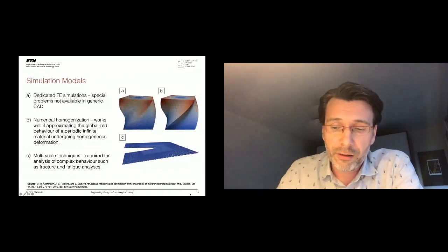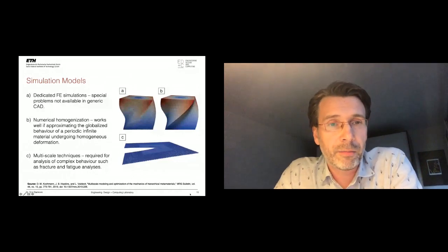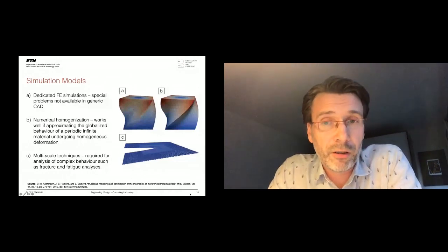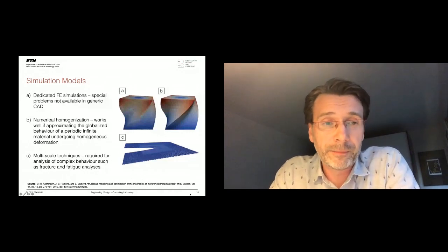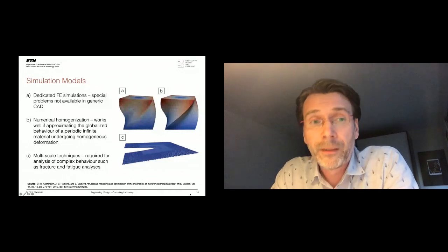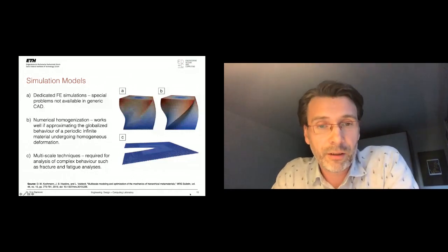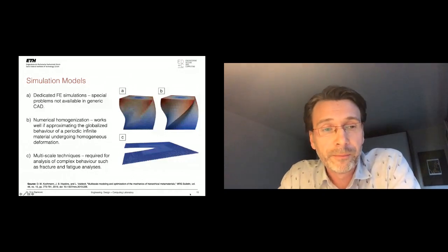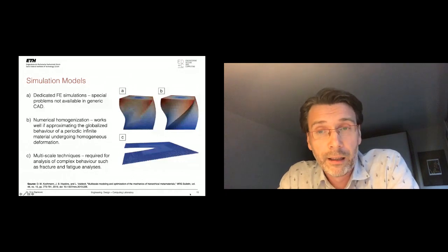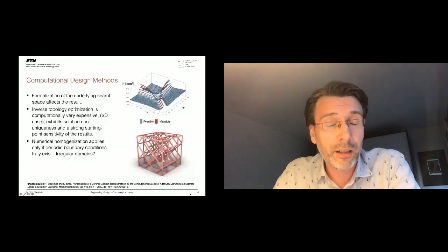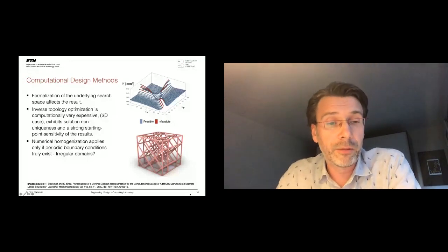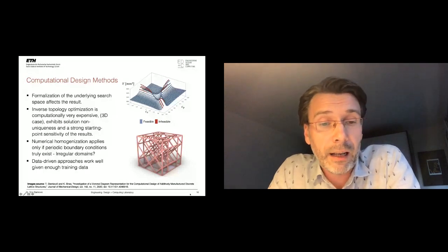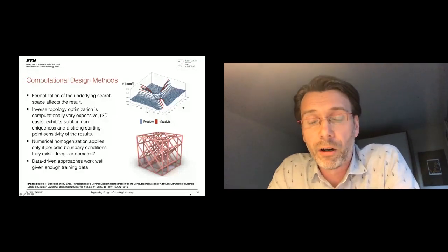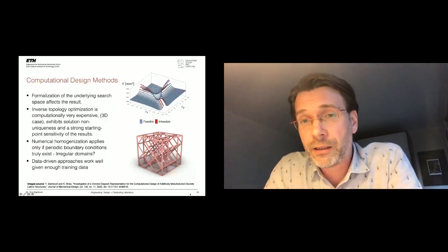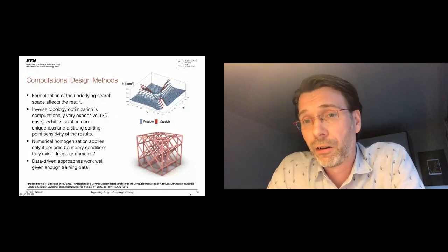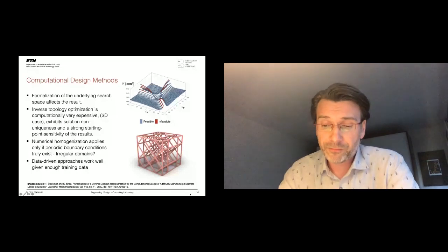Finally, computational design methods are also affected. For example, formalization of the underlying search space affects the result, of course. Inverse topology optimization works, but it's computationally very expensive and exhibits solution non-uniqueness and strong starting point sensitivity of the results. If we can't apply numerical homogenization, meaning periodic boundary conditions, then we have irregular domains for which we need to apply different types of optimization that are close to straightforward structural optimization. And we have data-driven approaches that work well, given enough training data. So in the example here, for this small parameterized topology-based optimization, you can see that the search space at the top right is completely non-convex. So these problems with the computational tools and optimization are very hard to solve.